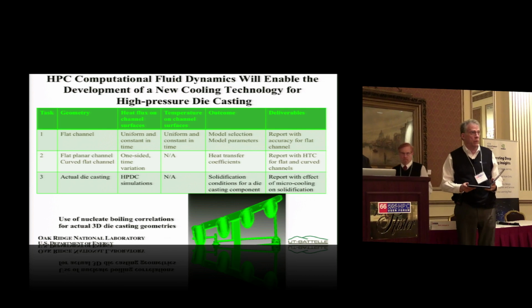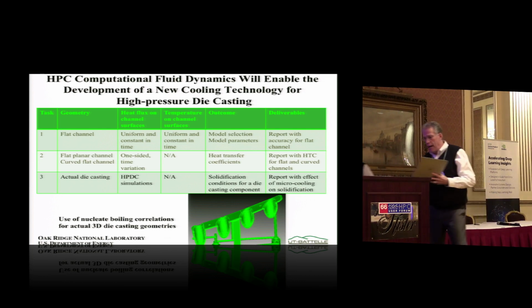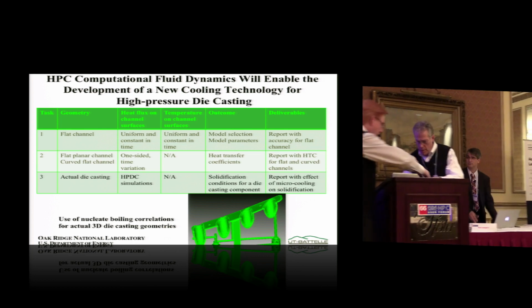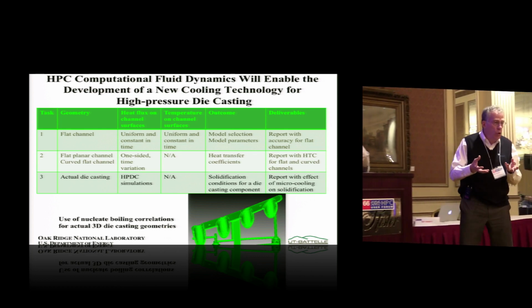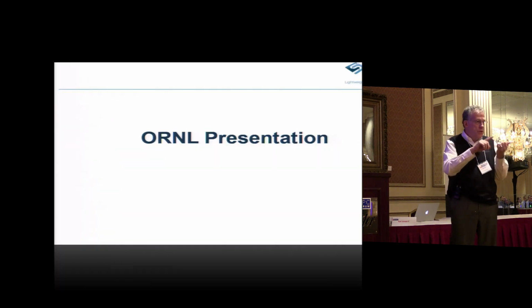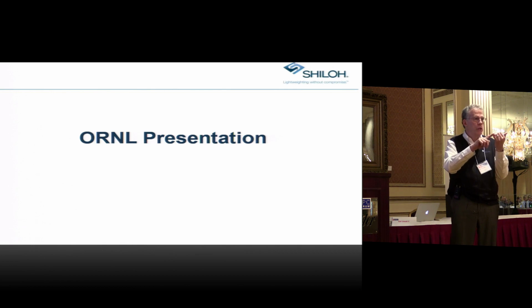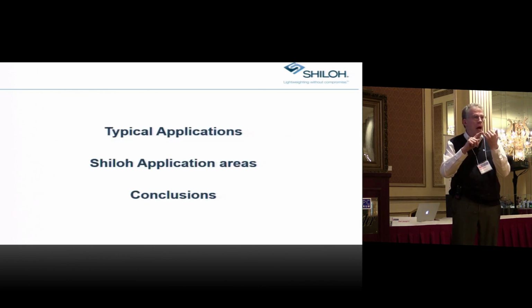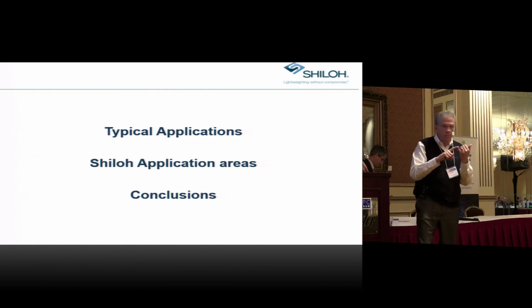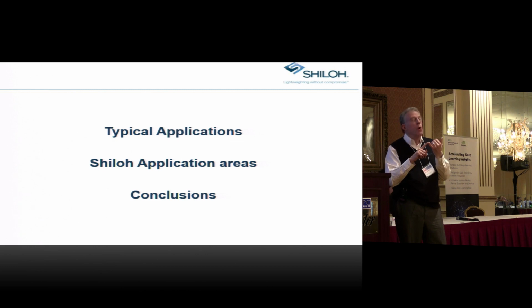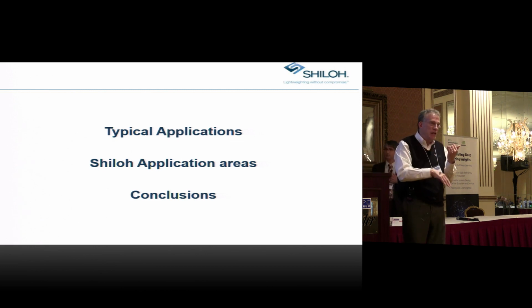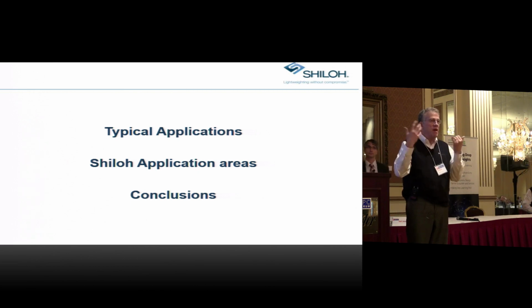So the next thing I was just going to mention is, why do we care? We're doing all this analysis, looking at how the cooling is going to affect the various channels and optimizing this case. The simple fact is that if we're too hot or too cold, the die life is vastly reduced. That means cost to the customer is extremely high. So let's say it was a typical die with a primary material which is kind of abrasive on steel to start with because it's got low iron content, because you're trying to optimize properties. Maybe you have 100,000 cycles.